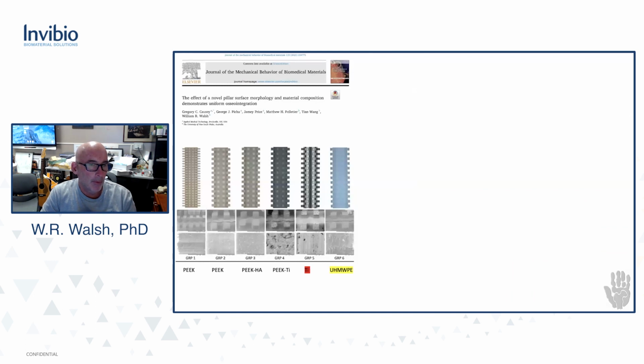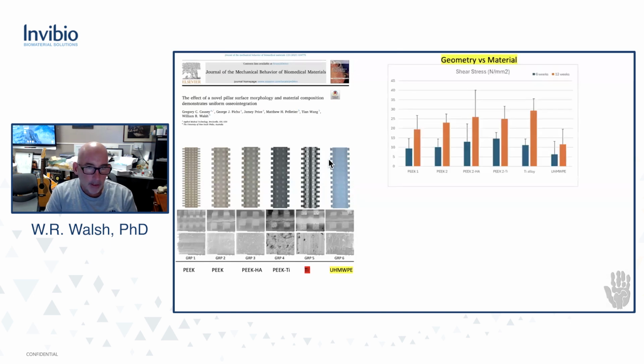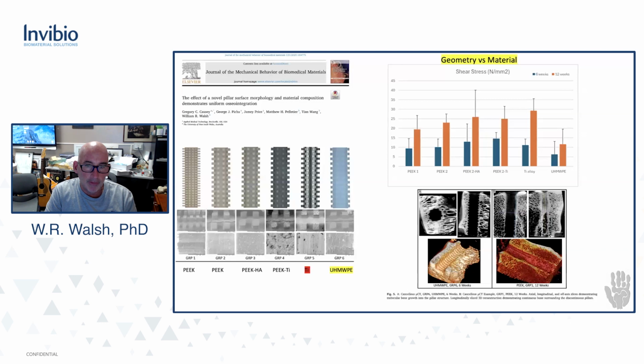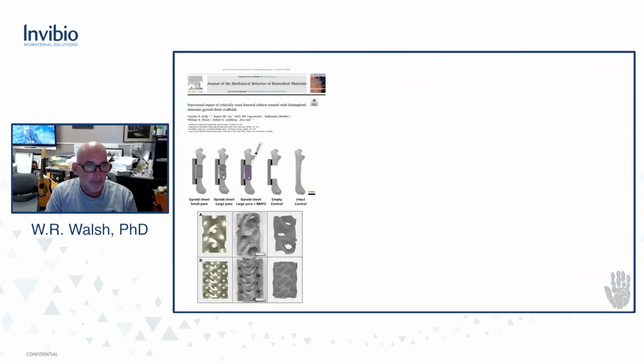And a follow-on paper that we did with Greg, in this study, we actually have PEEK with 2 different geometries. PEEK that had hydroxyapatite on it, titanium-coated PEEK, solid titanium machined, electrochemically grinded, and polyethylene. When we look at that, all the materials supported osseointegration, even the polyethylene. The polyethylene, when we pushed it out, deformed, but it supported osseointegration. We even see that in our micro CTs, because there's no metal artifact with the polyethylene or the PEEK, and we can see osseointegration, or bone growing into the available geometry that the implant provides.